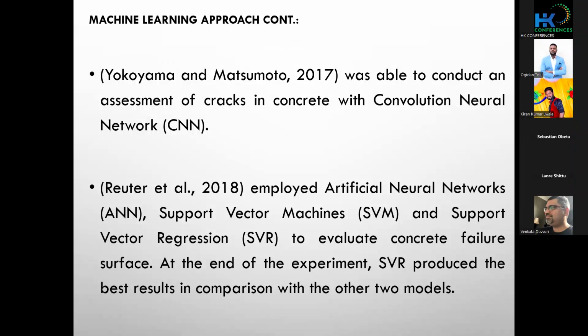So from this, Yokoyama in 2017 was able to conduct an assessment of cracks, just as we can see, in concrete with CNN, and also Reuter in 2018 employed artificial neural networks, support vector machines and support vector regression to evaluate concrete failure surface. At the end of the experiments, support vector regression produced the best result in comparison with the other two models. So that is for this. Let me next my slide.